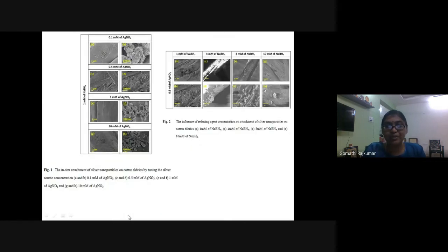So this is the image that you can see. This is the in situ silver nanoparticle on cotton fabric that we made by tuning the silver source concentration. You can see this is 0.1 millimolar AgNO3, 0.5 millimolar, 1 millimolar, and 10 millimolar, where you can clearly see the difference in shape and size. These were all very round, but when the concentration of AgNO3 increased, the particle size became more distinct. So this is one.